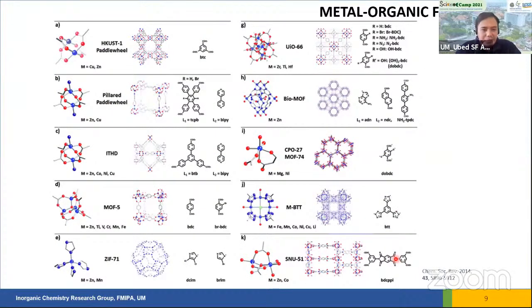Remember that we can use different types of metal ions and different types of organic ligands, so we can have various structures of metal organic frameworks. For example, the paddle wheel type of metal cluster. Here, 2 metal ions coordinated to carboxylate from the benzene 3 carboxylate will form such a type of structure. We can use copper or zinc in this case. But if we use zinc or manganese with the imidazole organic ligand, this is imidazole, we can have a different structure. This is the structure of ZIF-71, zeolitic imidazole framework. So this is very different from the one with copper and the 3 carboxylate ligand. Different types of cluster and different types of ligand will result in a different type of structure.